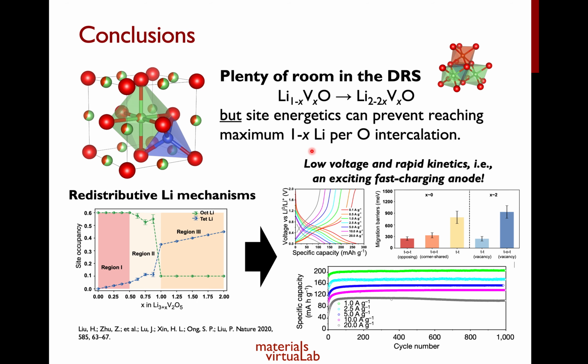All right, so to conclude, there are two important messages that I want to communicate through my talk. First, there's plenty of room in the disordered rock salt, okay? We can use a general formula of Li1-xVxO. We know that we can lithiate up to about Li2-2xVxO in the disordered rock salt, okay? However, site energetics can prevent reaching the maximum Li1-x lithium per oxygen intercalation, as I showed in my preceding slide, okay.